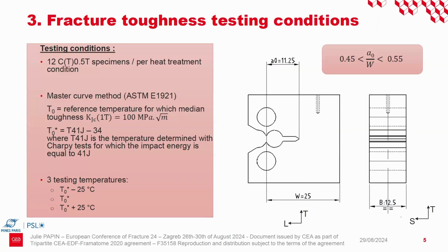And for the testing condition, for each heat treatment condition, we tested 12 CT 0.5T specimens, with the geometry represented on the right. We use the master curve method defined in the ASTM E1921. In this paper, the reference temperature, T0, is the temperature for which median toughness, KJC in 1T, is equal to 100 MPa square root meter.